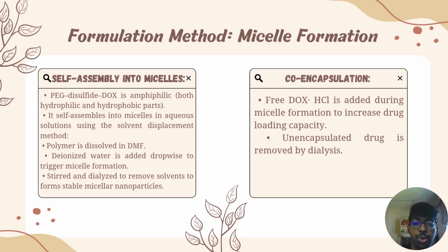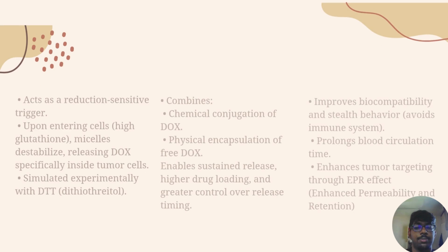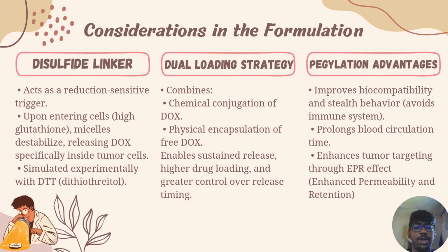effective drug delivery. To enhance the loading, free DOX HCl was added alongside the polymer before water addition. This enabled the micelles to carry both chemically bound DOX and physically trapped DOX, offering a dual release system. Finally, dialysis removed any free drugs, leaving us with efficient DOX-loaded micelles optimized for tumor-targeted therapy. One major strategy is the use of disulfide linkers, which respond to reducing environments, especially the high glutathione levels in tumor cells. Inside these cells, the disulfide bond breaks, leading to micelle destabilization and targeted DOX release.